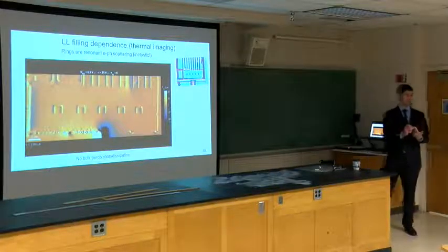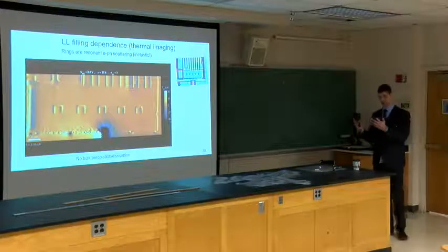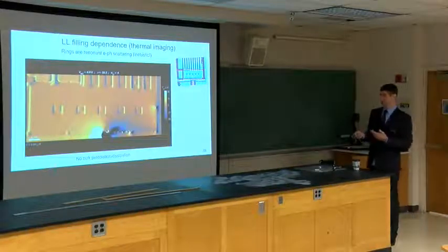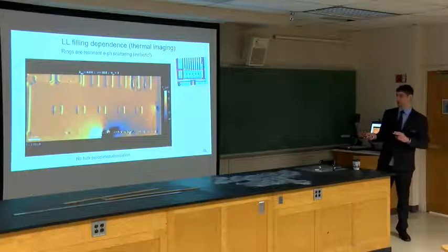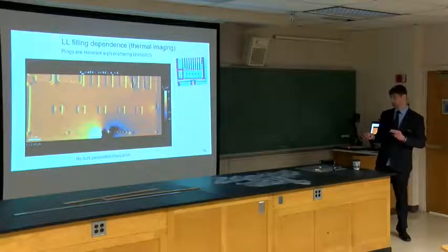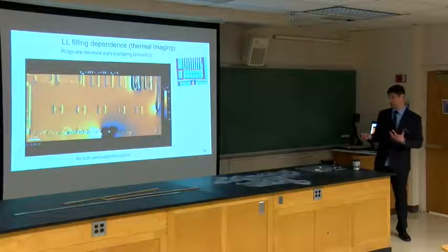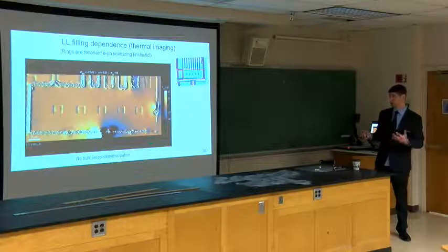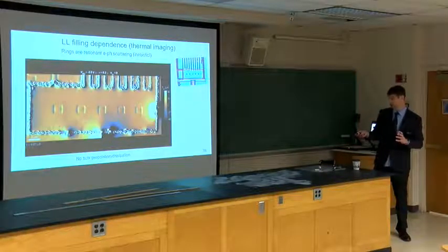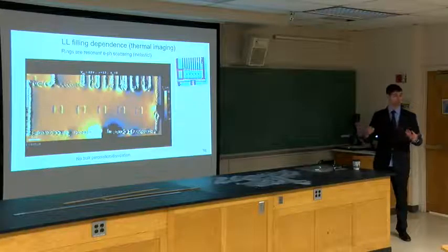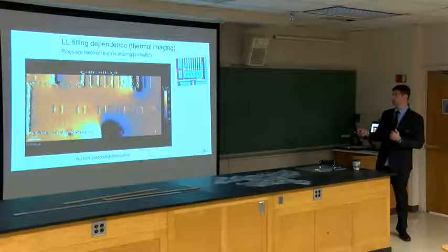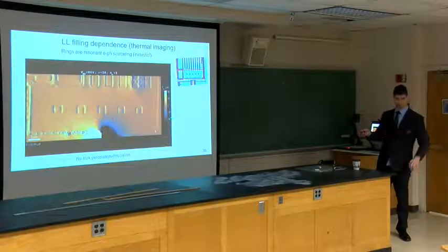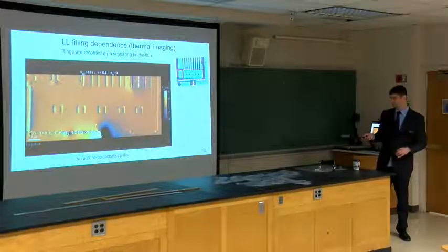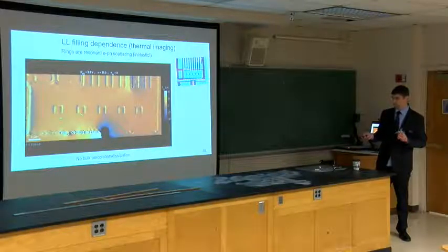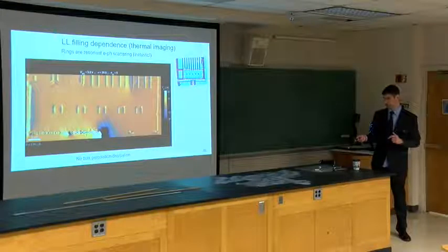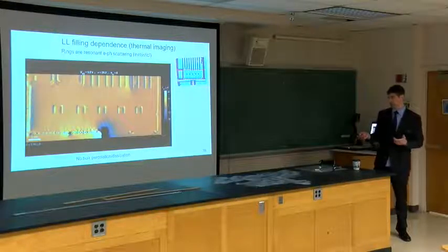That shouldn't happen, right? I mean, that was one of the hallmarks of this, that there's clearly dissipation in this system. And the second thing is that there's no bulk dissipation. So while the edges are lighting up, and this is all relative temperature change, the actual number here, we can't comment on what the actual change is, because it's not calibrated to that degree. So we do not see bulk dissipation in that none of these rings, which are resonant inelastic scattering.